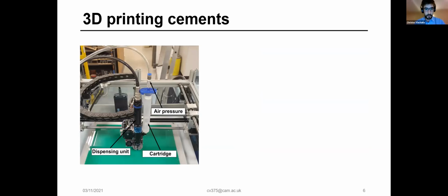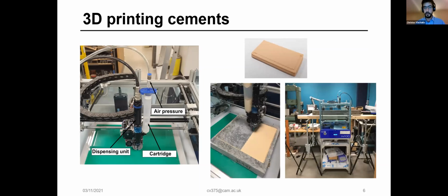Now, what we see here is just a very basic 3D printing setup. We have a dispenser mounted onto an XY gantry of a 3D printer, and this allows us to print the activated calcined clays that we mentioned earlier. We're able to achieve some rectangular blocks right here. Something else we can do is print directly onto concrete elements. On the left-hand side here, we see a coating being applied onto a concrete slab. And on the right-hand side, similarly, we have a coating being applied onto a reinforced concrete beam.